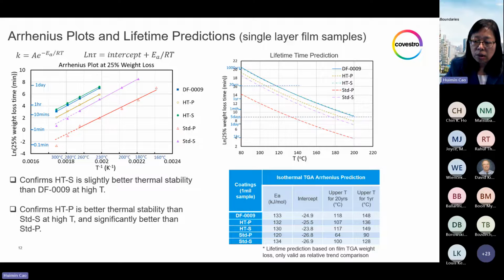And keep in mind, this is only valid in a relative sense based on this weight loss criteria from film study. For coated fiber, it is perfectly fine if you want to use different performance criteria for your lifetime prediction. You can use strip force, attenuation increase, or detection of any coating defect formation, and you can decide the upper use temperature for your short-term application, or the upper use temperature for your long-term application. Here is prediction based on this film TGA study.